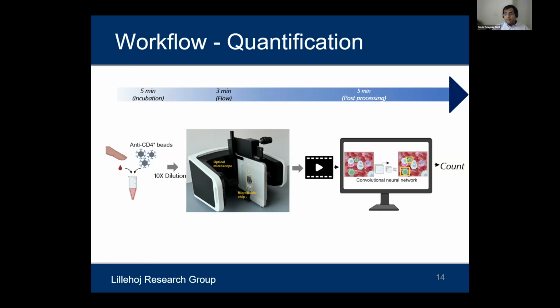So the overall time scale to do this is that for the incubation first step, we only needed 5 minutes because they are micron size beads. 3 minutes for the 20 microliter sample slug to flow and fall through the chip, and then 5 minutes for post-processing. I just wanted to tell you that the 3-minute flow timing and the 5-minute post-processing time can be overlapped because they are independent, and it could be a live inference.